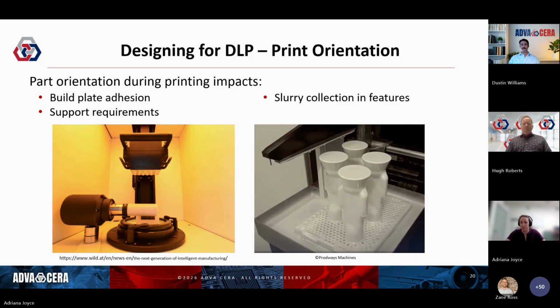On the Prodways printer, the light's coming from the other direction. The part descends into the vat as the layers build up from the positive Z direction. So we aren't fighting gravity, but the part is filling up with slurry. Any feature with a partially or entirely closed cavity is going to come off the printer completely full of slurry. It increases our slurry usage and increases the time required to clean parts. Additionally, the part has to be connected to the build plate well enough that it doesn't float up and away during the printing process or get knocked over by the slurry and the blade moving across during each recoat at the end of the layer.